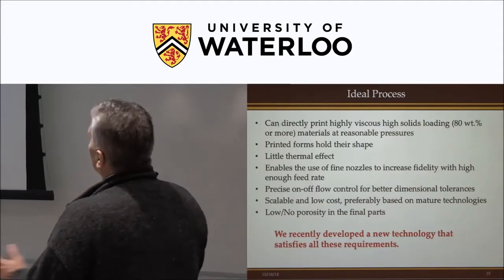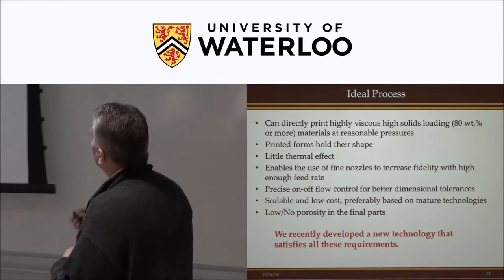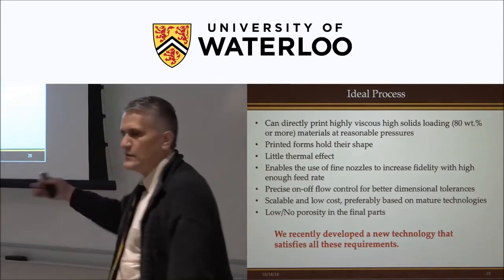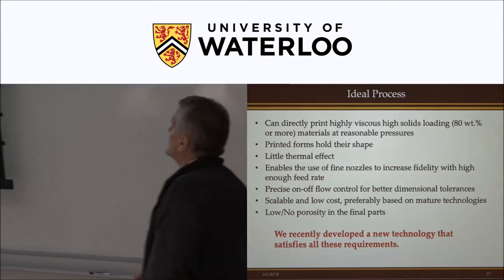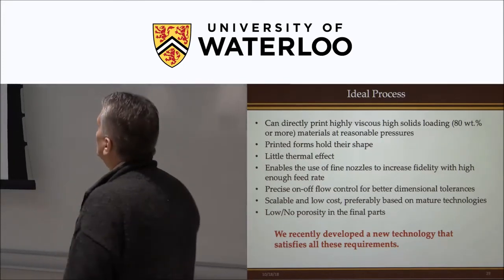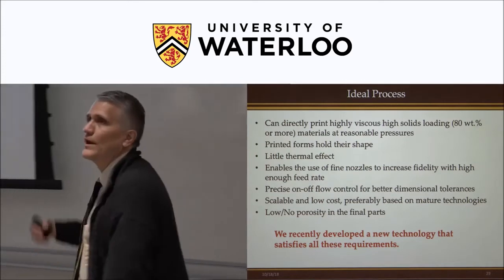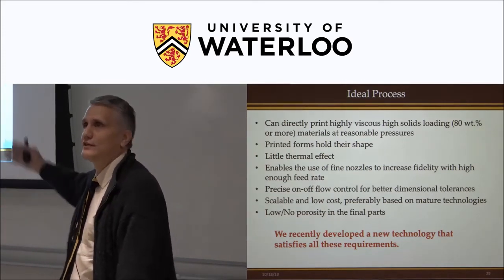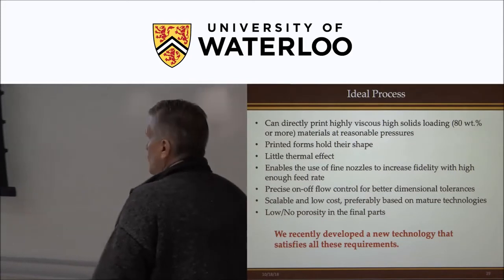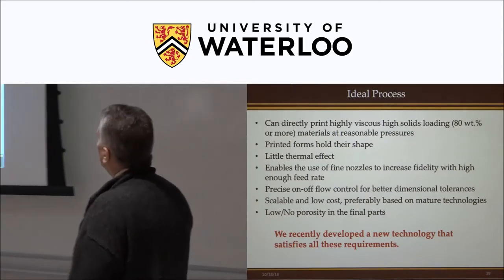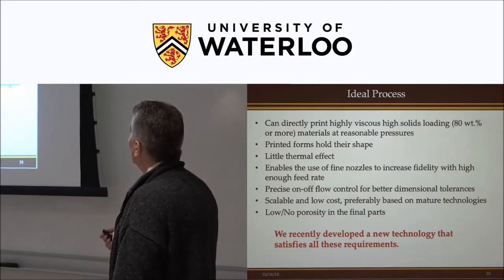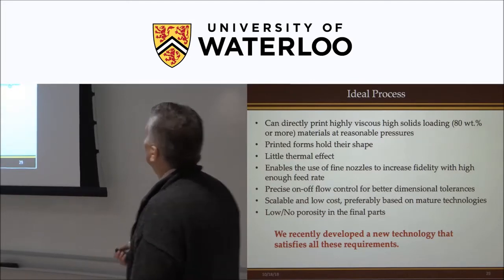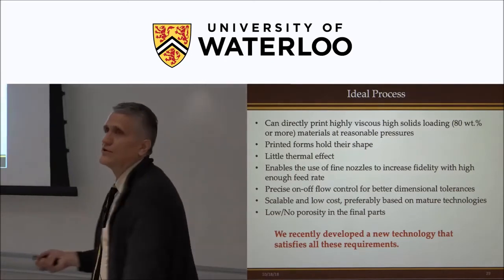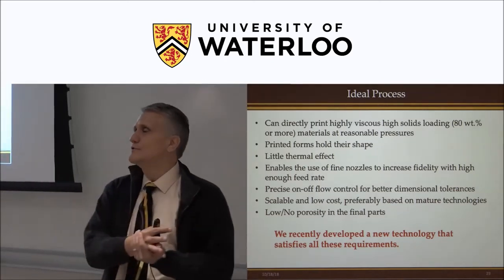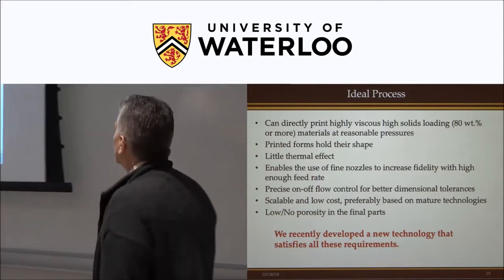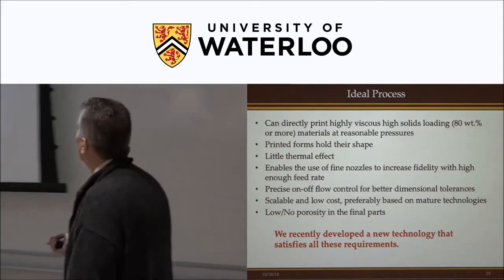So this is kind of the ideal thing. Ideally, we'd like to be able to go to at least 80% solids, certainly higher. High solids loading for solid propellants is like 88, 90%. We want the printed form to hold the shape. We want little thermal effect because we don't want to heat these materials up because they're propellants, right? They'll ignite. We want to be able to precisely turn the flow on and off to control dimensional tolerances. We want it to be scalable and low cost. We want low to no porosity in the final parts. If our propellant has porosity, the flame is going to get into those small gaps, pressurize, and open up cracks, and then again, it's an explosive. It's no longer a propellant or a rocket.